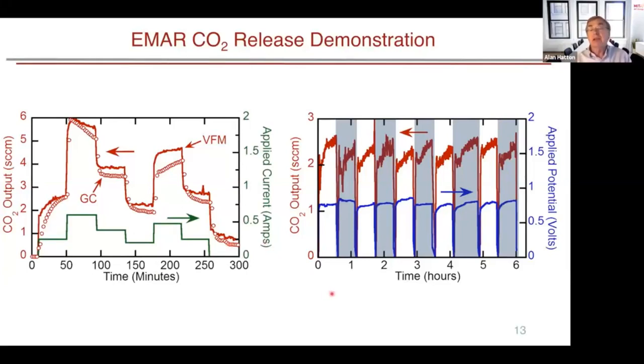Obviously, what happens is sometimes the anode will be corroded, and the cathode will grow with time. And at some point, we will need to flip chambers, change the polarity, and switch the feed to the different chambers. And this shows you the cyclic type operation is rather stable. This is on the order of 6 hours. We've actually run these for more than 200 hours now, and we've got very, very stable operation of these systems.